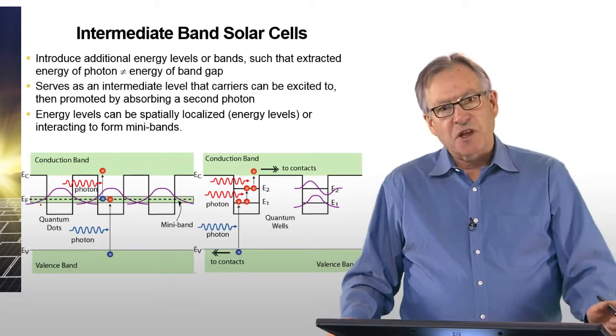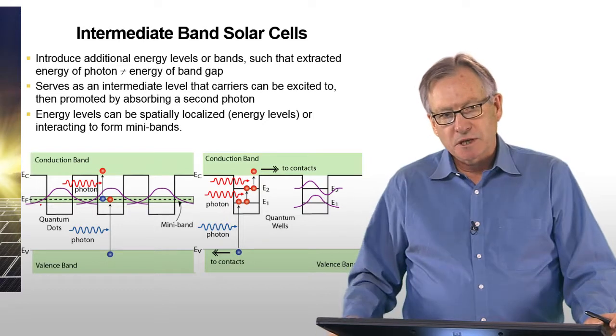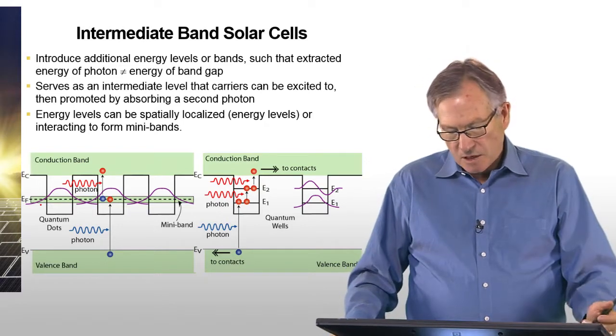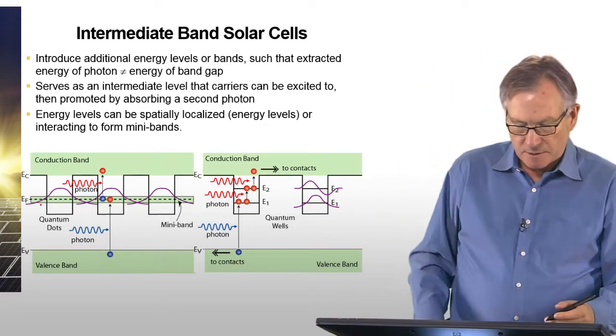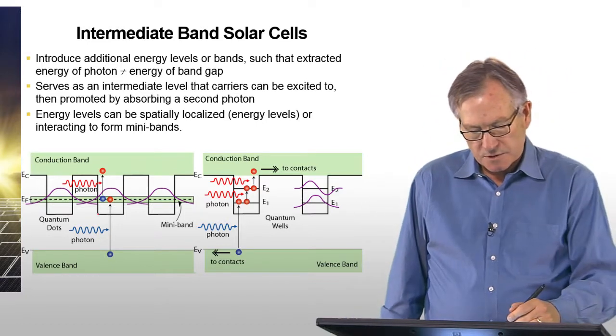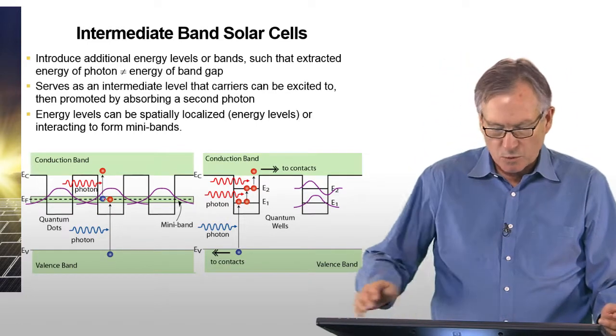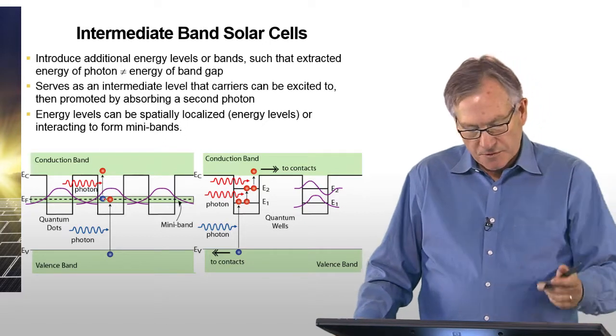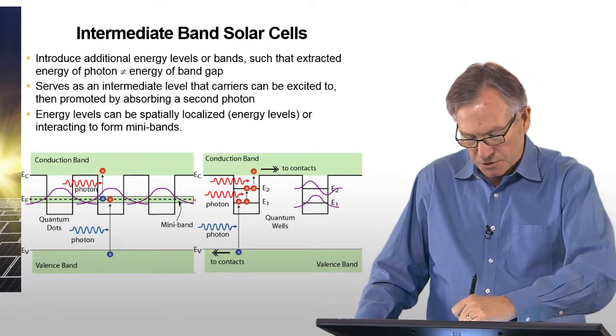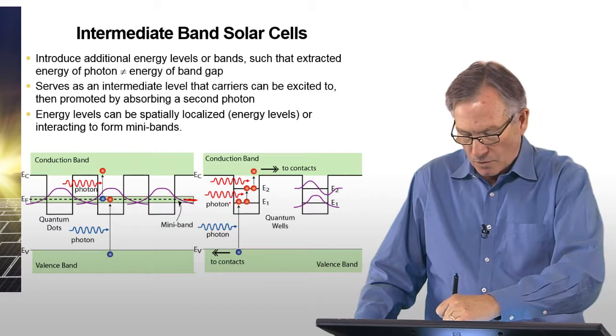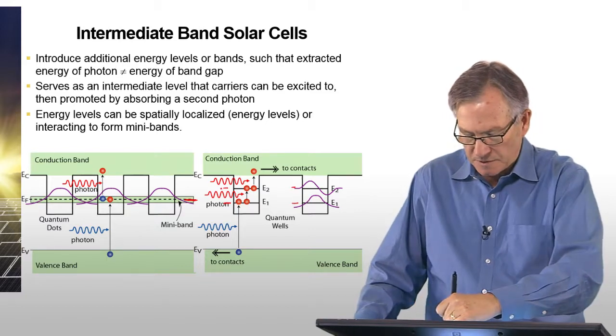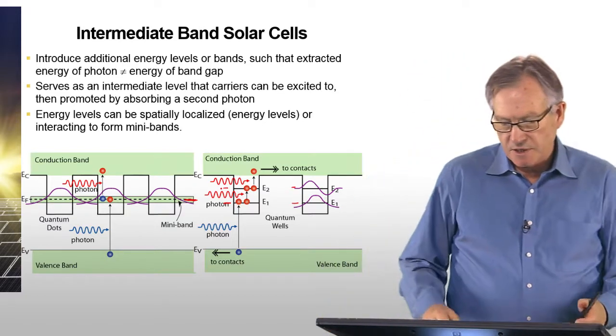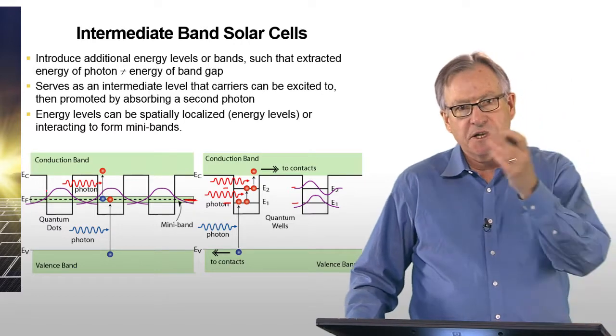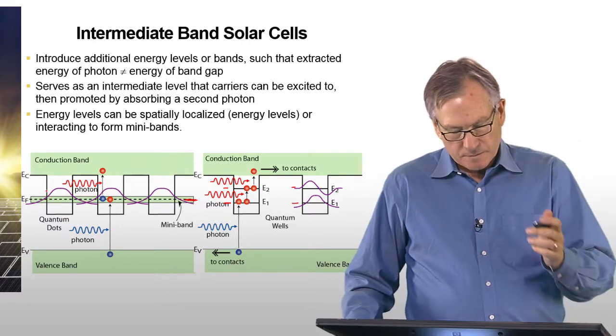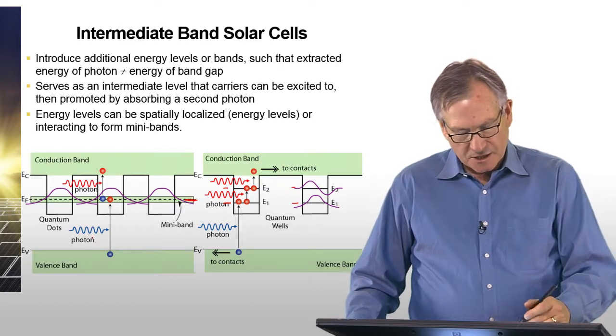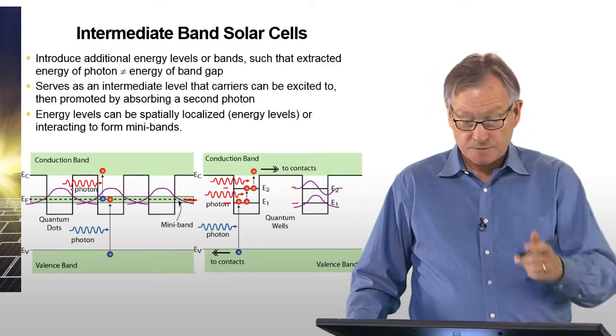Quantum dots can be grown in the same way, and I'll discuss a way that that's realized using molecular beam epitaxy. But the main idea is that this superlattice of quantum dots or quantum wells, because of quantum confinement, has an energetic level, which is shown here, or these levels E1, E2. Anyway, there's a series of levels, and this level then acts as the intermediate band, allowing the electron to park itself when it's excited by a subband gap photon.